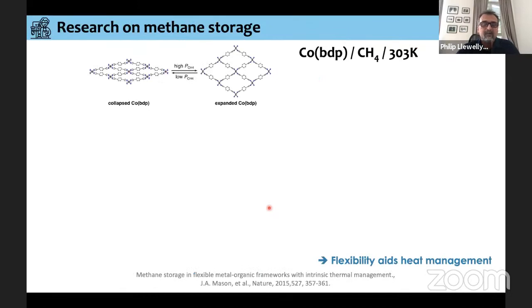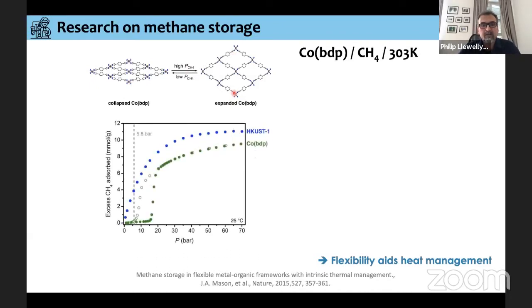So moving outside a little bit the idea of metal nodes, linkers and ligand functionalization, very quickly looking at the problem or the advantage of maybe having a flexible material. In this work by Jeff Long's group, we can see that they've been looking at methane in a material which is highly flexible. We can see here that initially the material almost has no porosity at all. And as they increase the pressure, the structure opens. And the isotherms look like this.